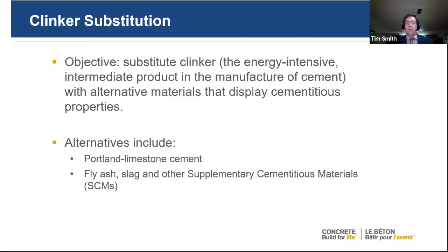What the easiest low hanging fruit is actually clinker substitution. And there's two main ways of doing that right now. One is to use the Portland limestone cements. As I mentioned earlier, in Europe, they're actually using this commonly, and they're at 20 to 30% substitution of limestone, where we're at only up to 15%. So they've been utilizing this technology for some time, and we're just starting to catch up to them on that.